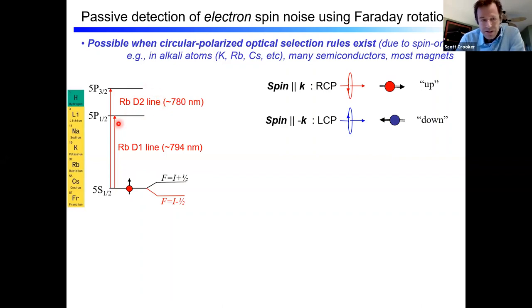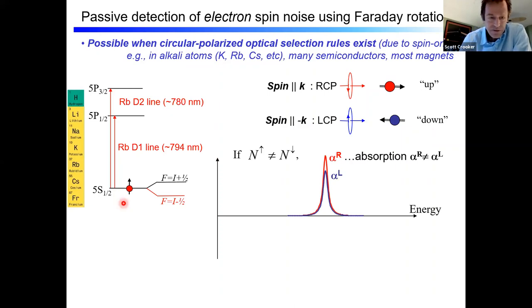And what that means is that if we tune the laser to this transition or this transition, we have optical selection rules, namely meaning that if this electron spin is oriented parallel to the incoming light direction, it couples to right circularly polarized light. But if this spin is pointed anti-parallel to the incoming light direction, it will couple to left circularly polarized light. And what that means is that if I'm studying a box of spins or a box of such atoms, this gives me a very powerful means to measure magnetization using light.